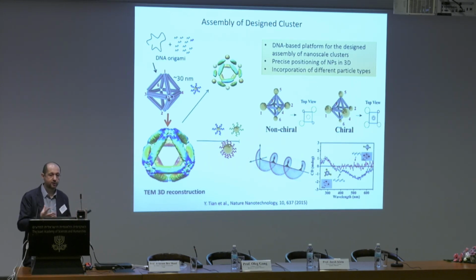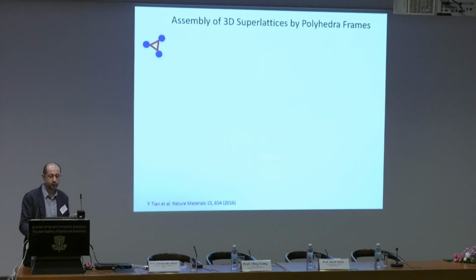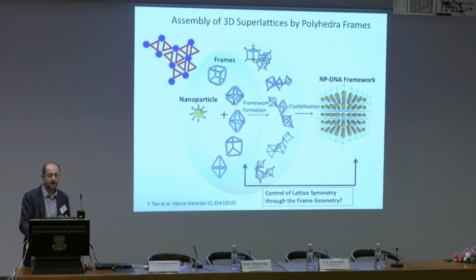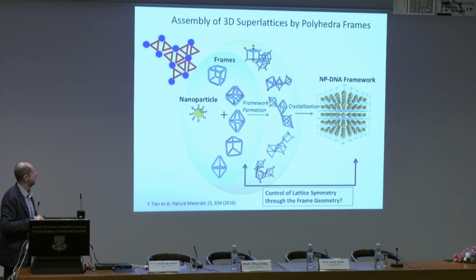So now, having this idea for building particles into finite-size 3-dimensional clusters, one can explore why not use this as a way to cross-link particles in 3D. And that's the approach which we have been exploring here. You can generalize the particles now using this type of DNA frames, and that allows us essentially to position particles in this kind of DNA nanoparticle framework.